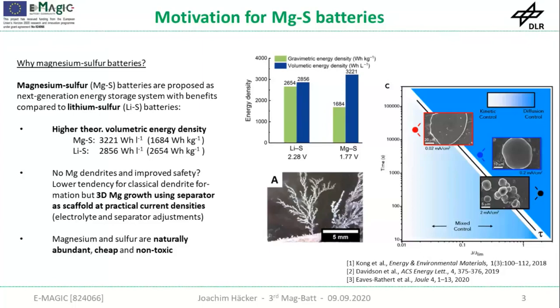Yeah, indeed, the overpotentials are quite high at the moment, and there is definitely room to improve. This is one thing I mentioned in the last slide. We want to examine some redox mediators together with DTU to access the second plateau, where most of the capacity is gained from, which is opening, I would say, the field for high energy density cells. But yeah, there's a lot of work to be done, and at the moment the magnesium ion cathodes look more promising, especially when you have a look at the cycling performance. So the capacity decay is also quite severe in magnesium sulfur.